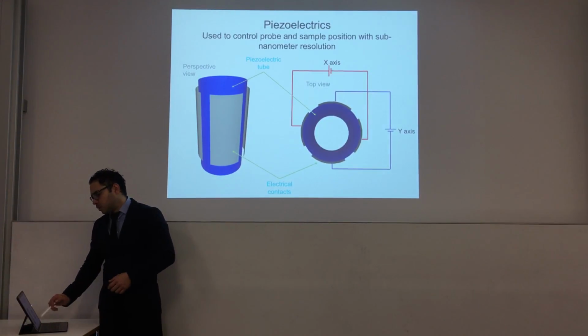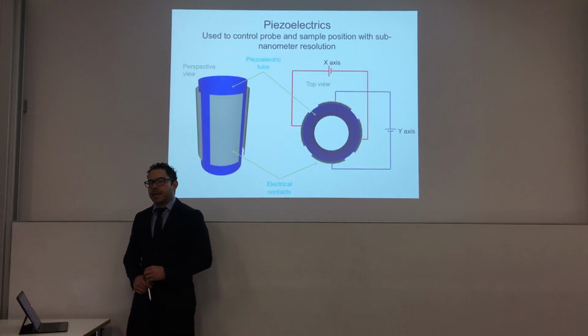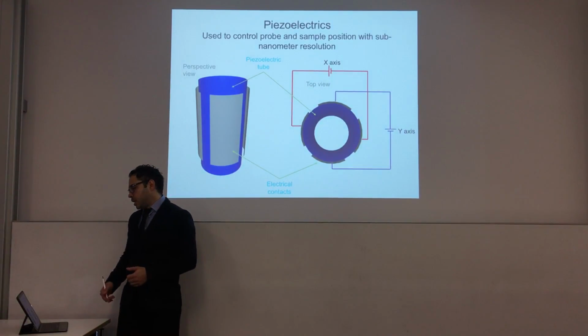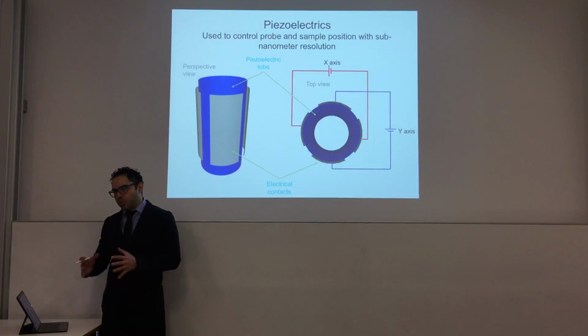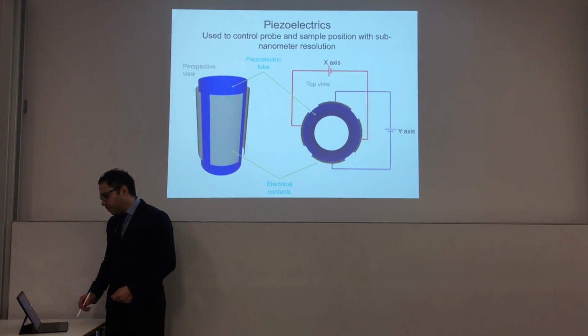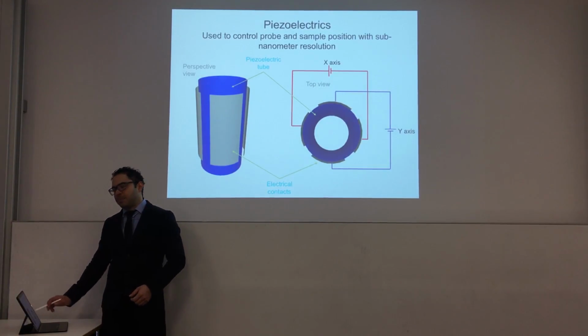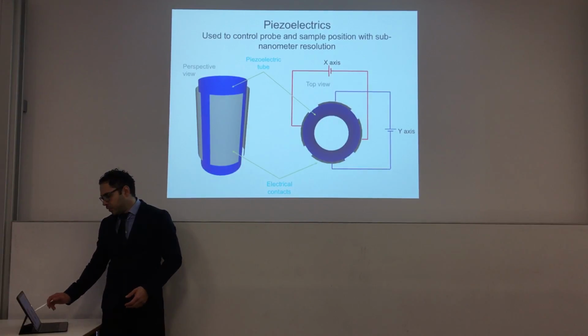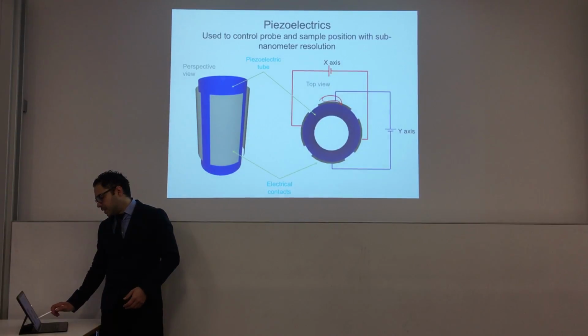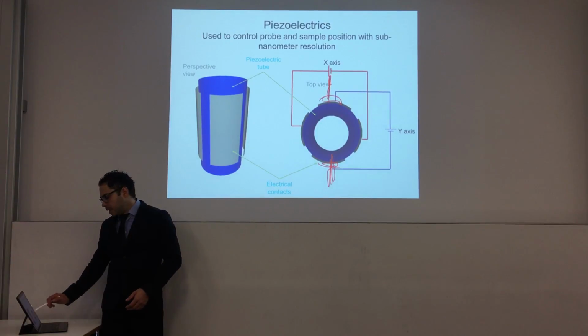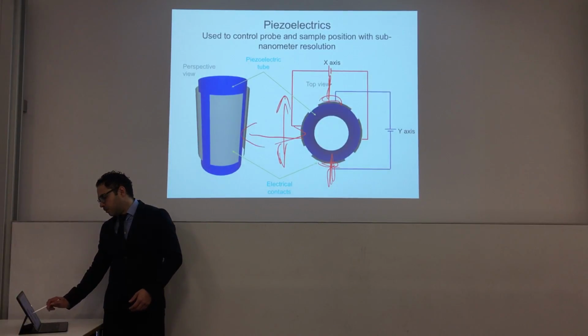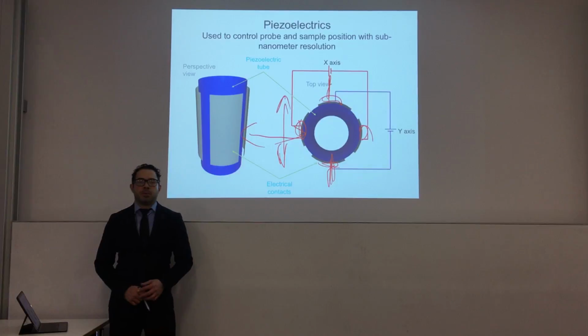For example, this is a piezoelectric tube. It's a classical architecture for an STM, for example, when you want to have very small movement with a very high precision. You have a piezoelectric tube, and you have different contacts on different sides, so that if you apply a potential difference between this one and this one, for example, the tube will deform in this direction. And the same will happen, of course, if you apply a potential difference in the other opposite directions.